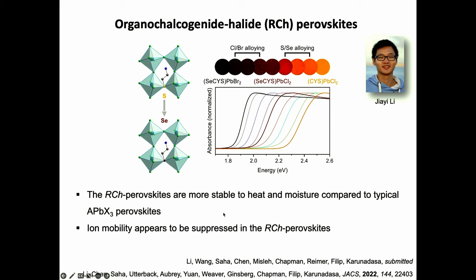So overall, these materials that I'm going to call RCH perovskites have successfully reproduced the band structure that we were trying to access. I didn't show you these data, but these materials are much more stable to heat and moisture, because we have covalently tethered this molecule to the framework. And we have taken 2D lead NMR studies that show much less ion mobility in these materials. So that means the halide segregation that I told you about previously is greatly suppressed in these materials. So these materials have a lot going for them. Again, they can be made through solution state chemistry, so highly scalable. And we are really focused on trying to figure out what this trap state is, can we quench it, and can we extract photocurrent from these materials.